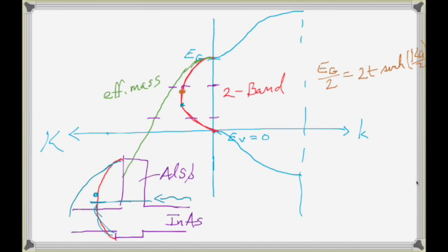In general, as you move away from the band edges, you can think of this as a correction to the parabolic model. This is parabolic, and this is some correction. Close to the band edge, parabolic is always fine. As you move further away from the band edge, either in the tunneling problem or in the propagation problem, that parabolic model is going to break down on you. So this is where you need a better band model. Okay, that brings us to the end of this first section of simple band models.